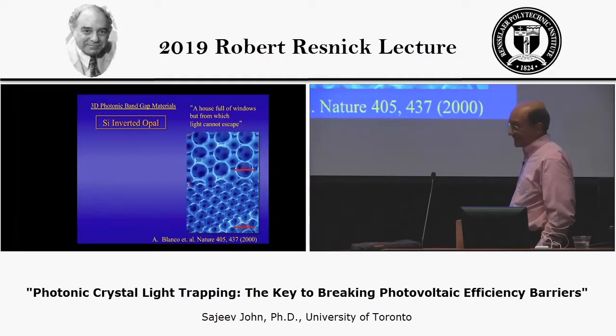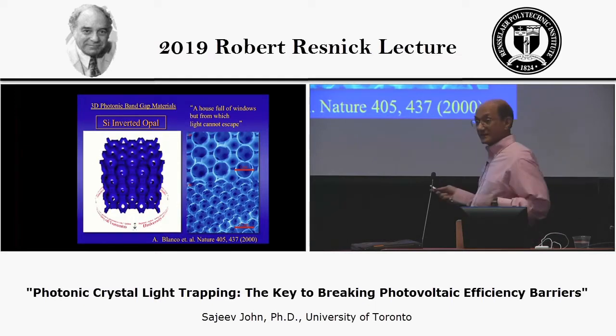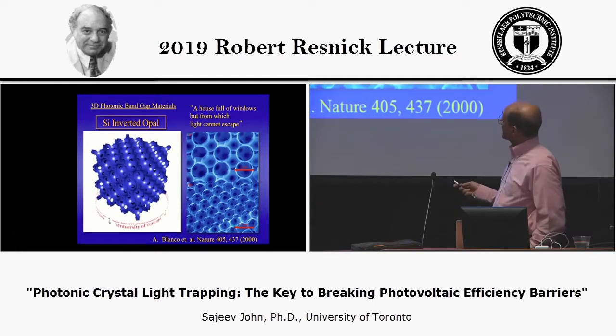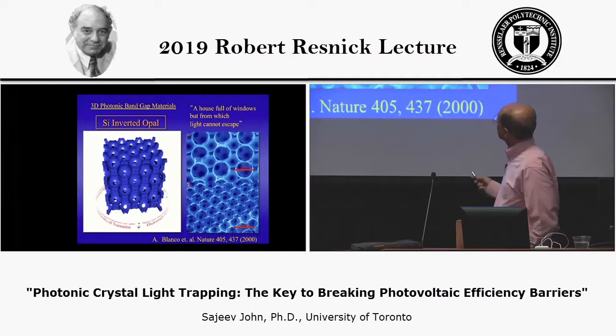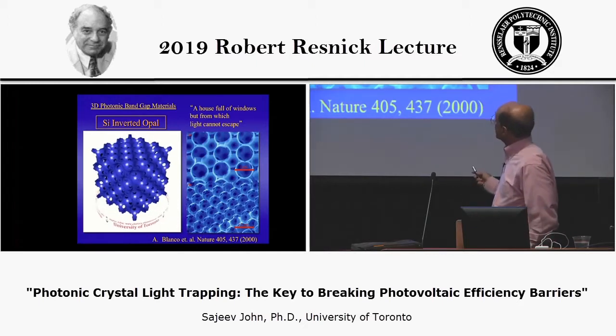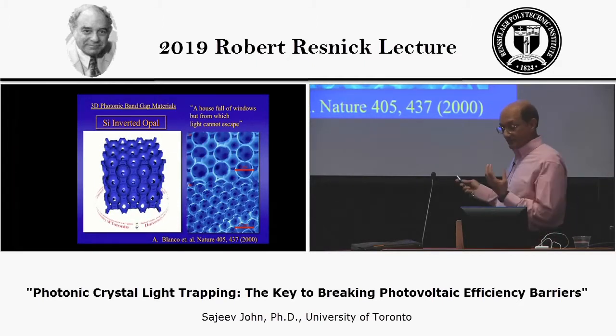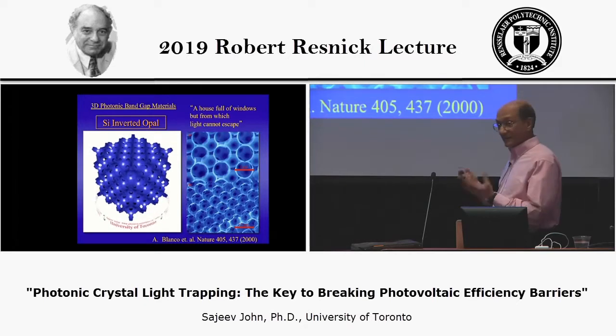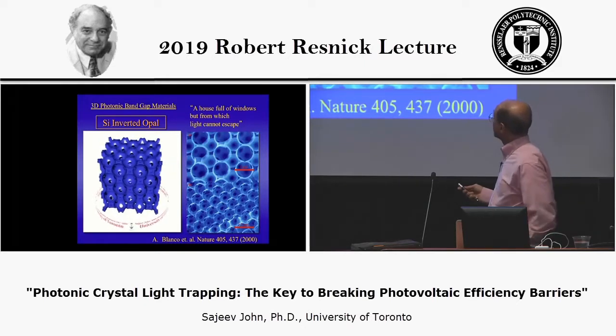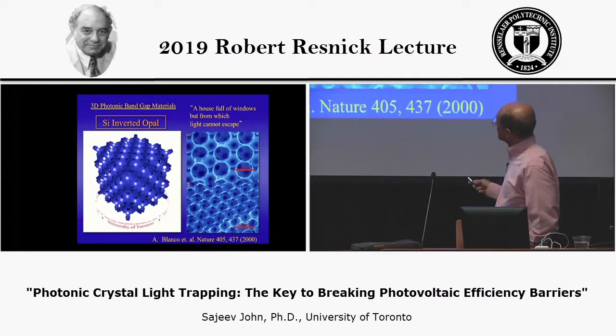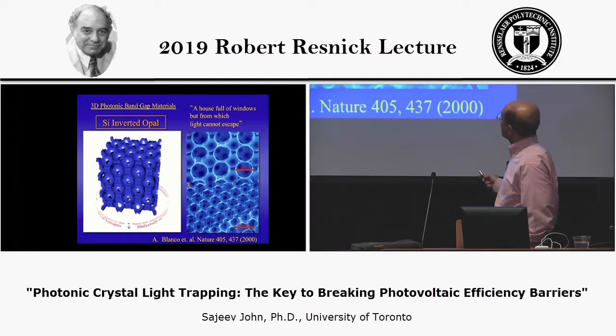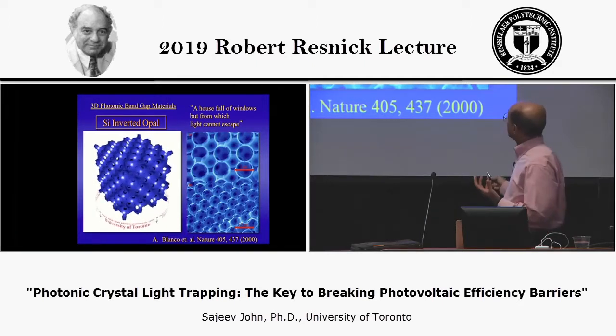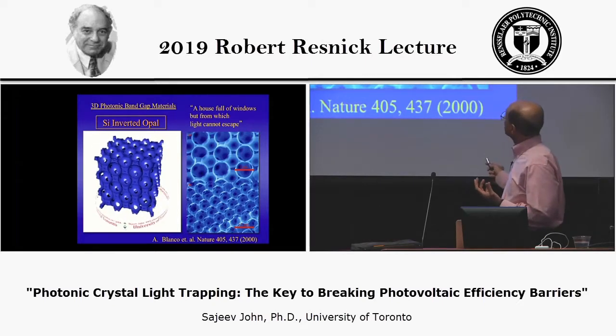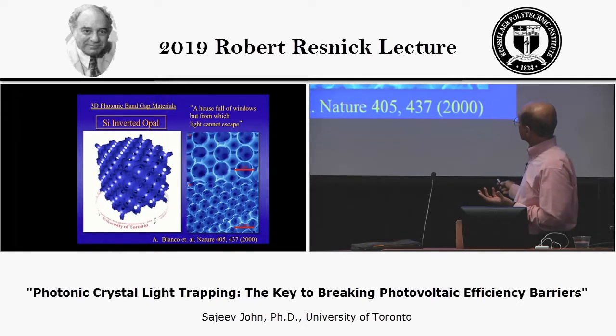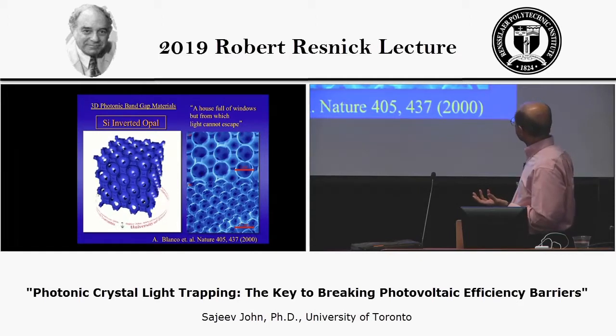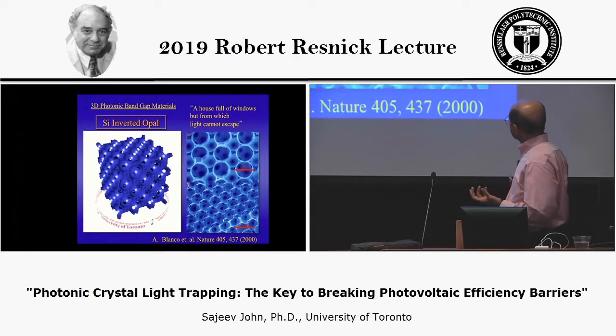And here's a depiction of a photonic crystal that I was involved in making. It's a material made out of silicon, created by starting with a template consisting of opals, dielectric spheres made out of silicon dioxide, and then infiltrating this material with silicon and then etching away the original silicon dioxide template, leaving what is called an inverse opal structure. So this is an SEM picture showing the actual structure here.